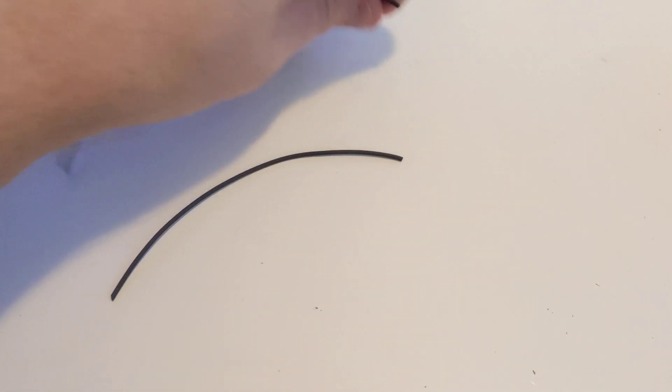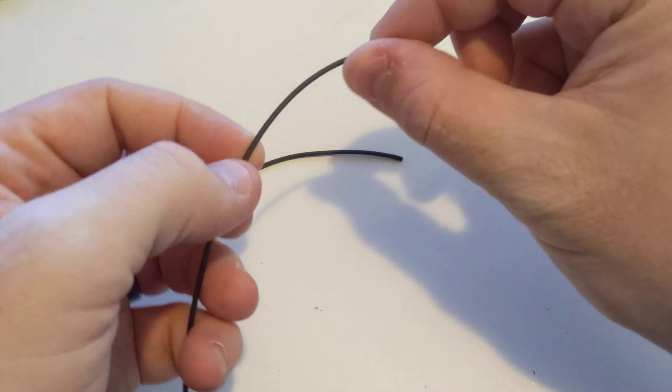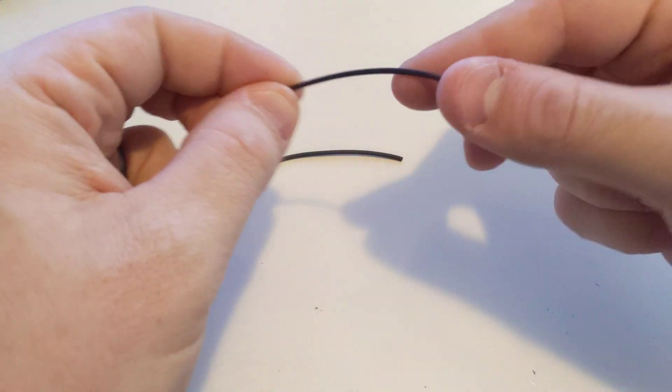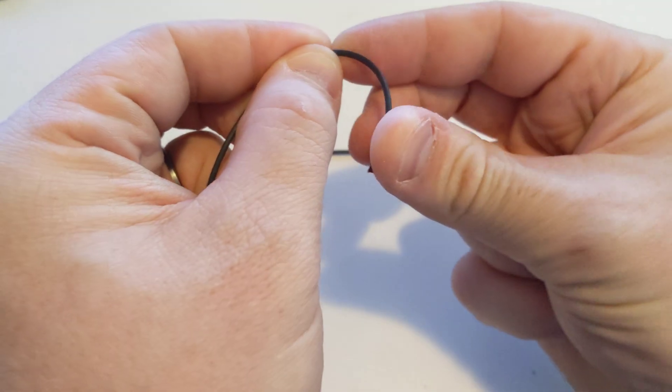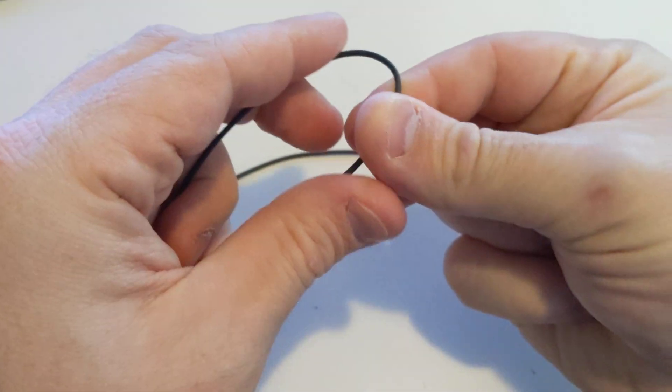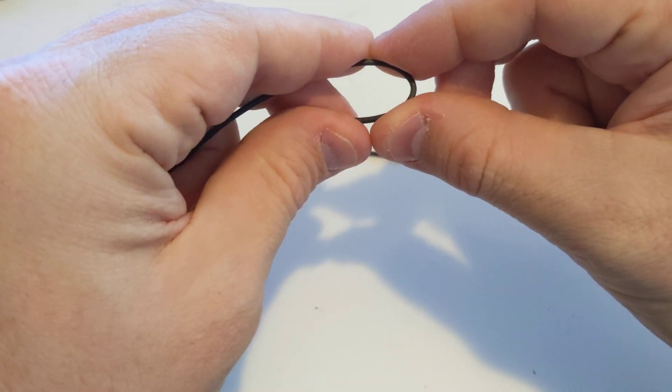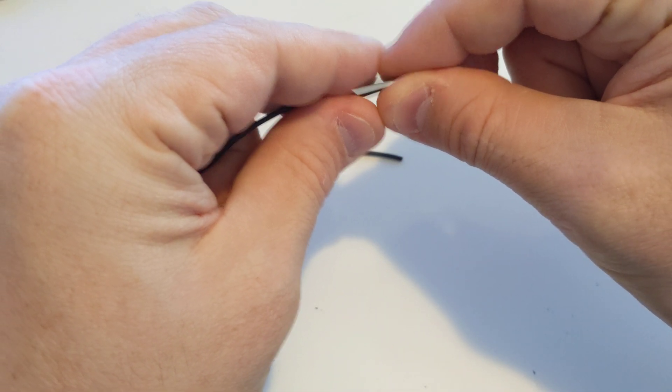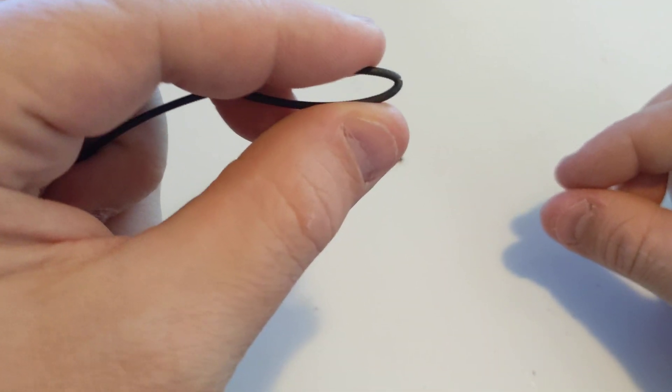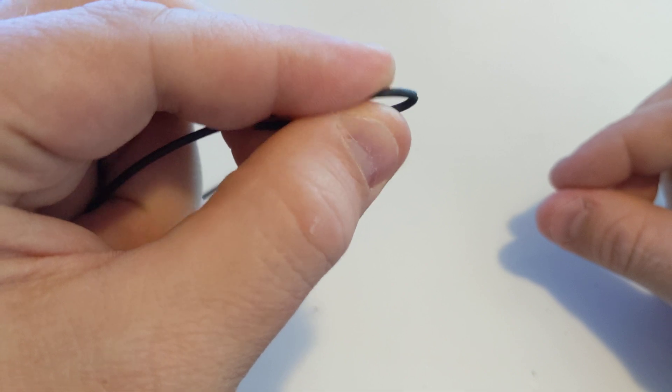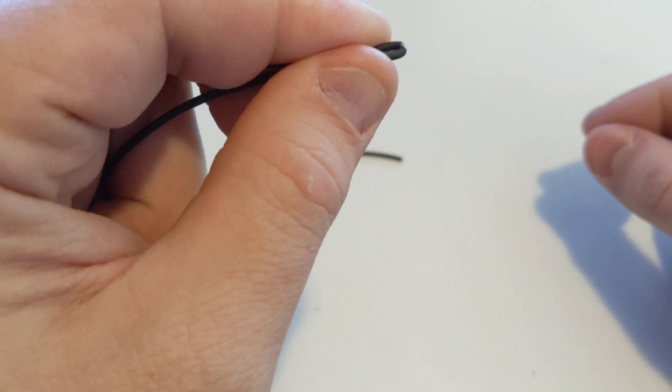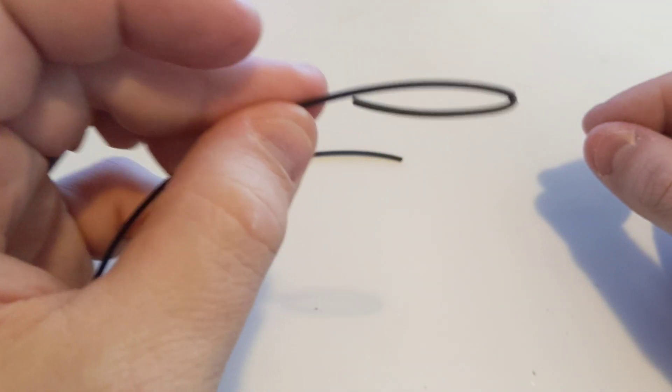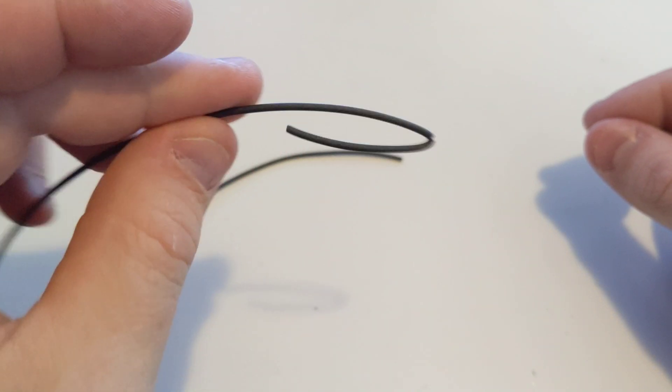So if your onyx has been sitting in the printer for a while and you're getting bad print results, take a piece of it out and try to see if it'll snap when you bend it. And if it doesn't snap and it bends like that, it still might break, but this is onyx that has absorbed too much moisture. This is not what you want.